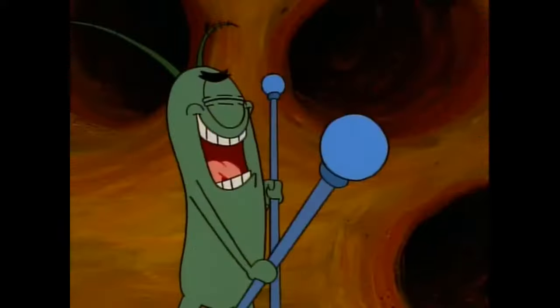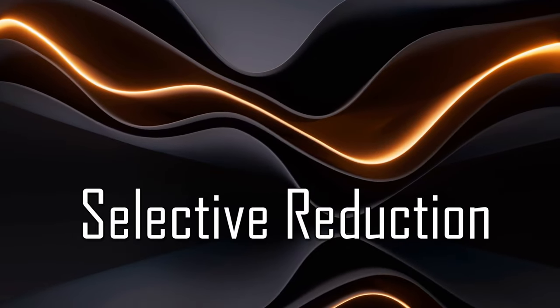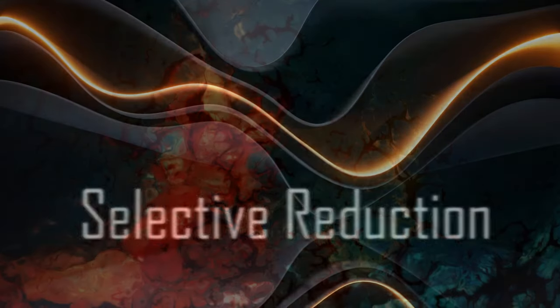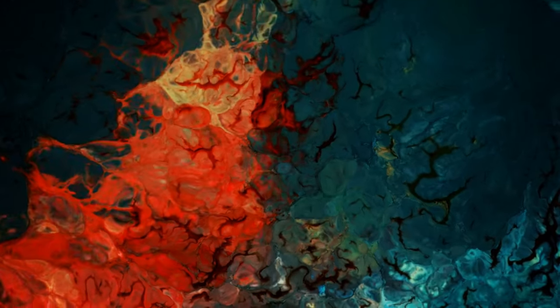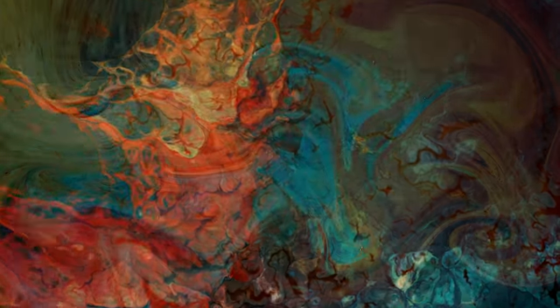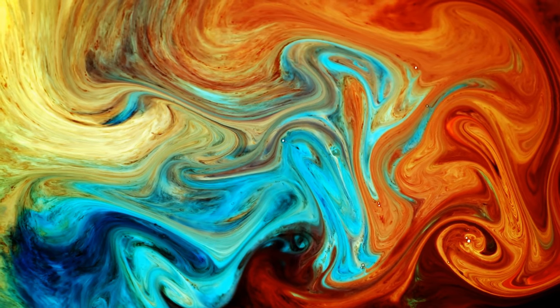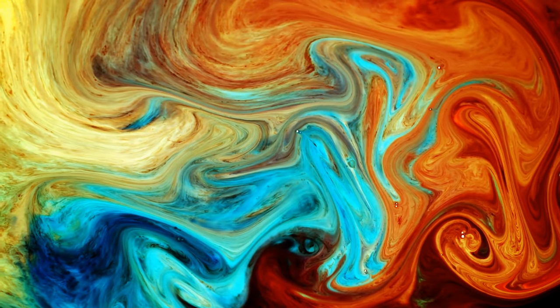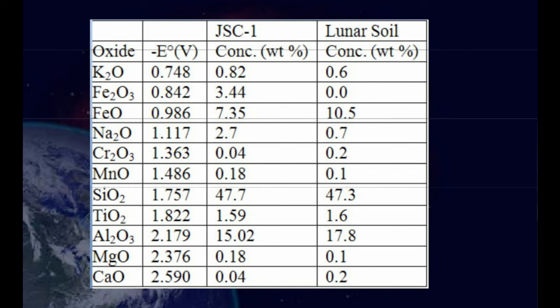So, theoretically, we can vary the voltage in the cell ever so slightly to reduce one element at a time. This concept is called selective reduction. Varying voltages precisely isn't actually that hard in its own right. What makes it harder is all the simultaneous reactions happening throughout the entire system, which can create different conditions with different demands, little pockets. So it's more of a game of averages, requiring you to cast a wide net, but also be very precise. Given the voltage difference between iron and silicon is 0.8, it's likely big enough to work with. However, it'll be much harder to separate chromium from iron, given the difference is only 0.4 volts.